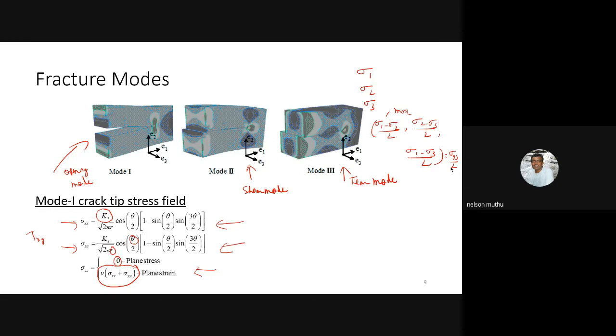Okay, so in the case of plane stress, the third principal stress, sigma 3, is going to be equal to 0. So if you bring in this expression, sigma 1 minus sigma 3, which in this case is sigma 1 minus 0, should be equal to sigma ys by 2. Therefore, your sigma 1 is nothing but sigma ys. This has been the basis for us to find the plastic zone correction factor in the case of the first order estimate. We also said that sigma 1 is equal to sigma ys, if you see carefully, along theta equal to 0 degrees, because that ligament is our focus.